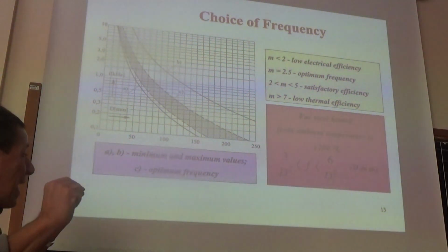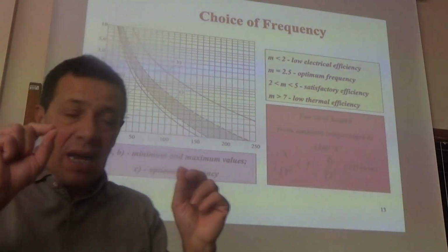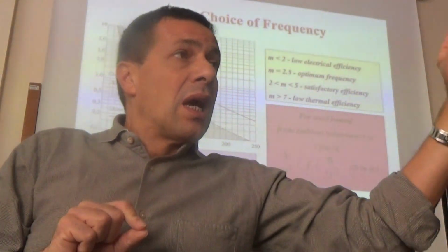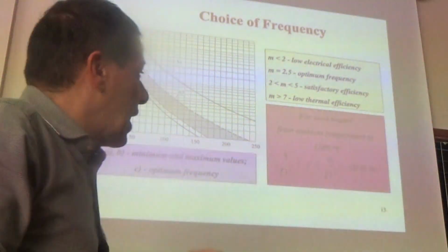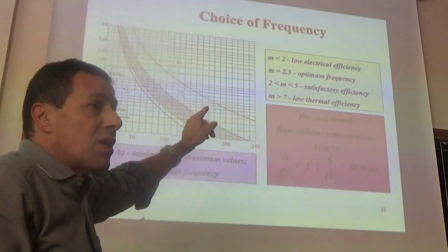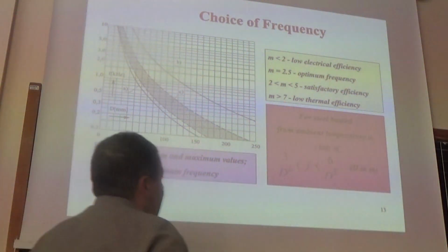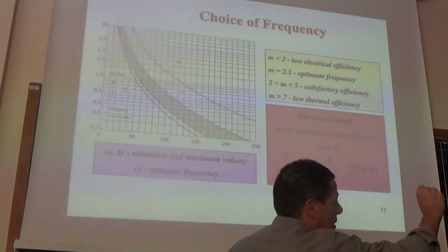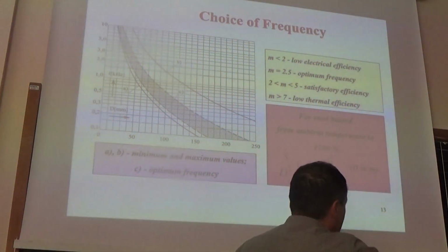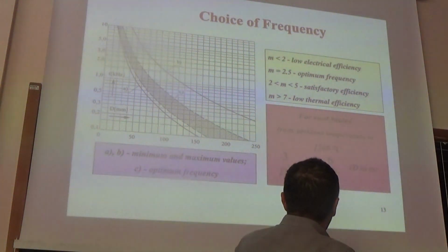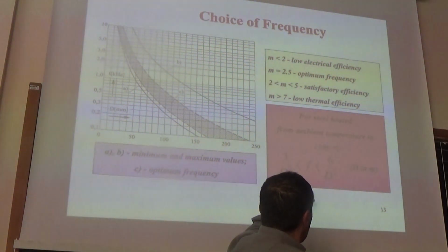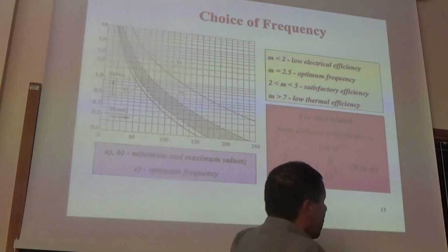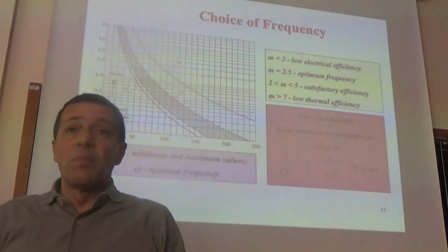So if we combine the proper conditions for high electrical efficiency, and we take into account also these considerations, and we do some algebraic passages from the traditional formulas, we can have a choice of the frequency between 3 and 6 ratio the square of the diameter of the billet.